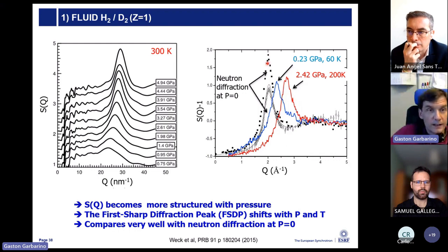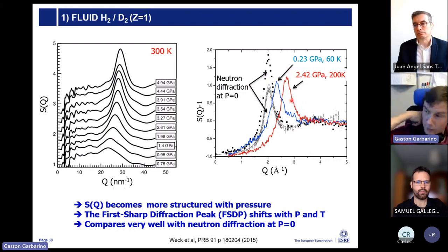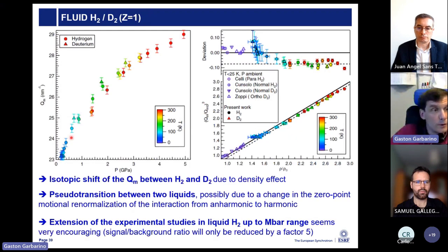Okay, and we can compare here in black dots the signal coming from neutrons. The thing is that to get signal from neutrons, you need to count very long. Now with counting times of the order of a minute, we were able to get the signal, and we are also able to couple with low temperature, and we were able to show how we pass from one type of liquid hydrogen at very low density to another type of liquid. This possibly shows the effect of the zero-point motion, of renormalization, and of the interaction from anharmonic to harmonic oscillation of the atoms.